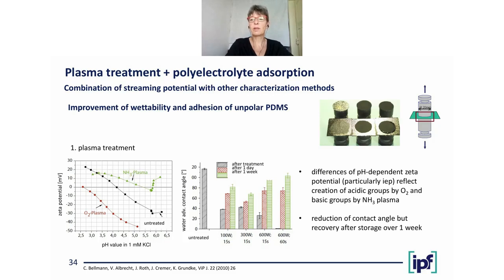But the problem with plasma treatment is that it's not very stable, so the surfaces recover with time. But what you can see in the Zeta potential measurements on the left-hand side is that if we use oxygen plasma, we create acidic groups. We get an isoelectric point at pH 2.5. If we use ammonium plasma, we get alkaline ammonium groups and an isoelectric point at pH 5.5 approximately.